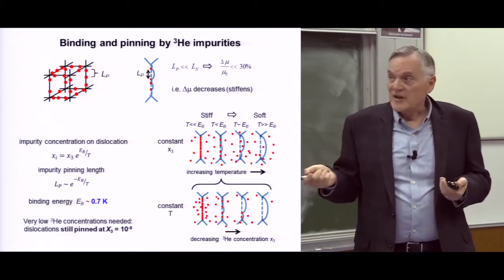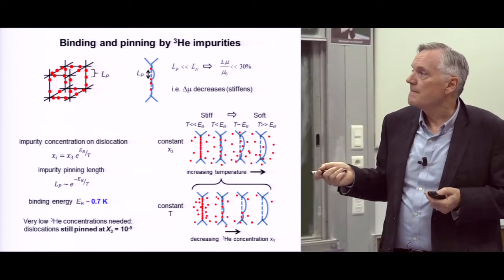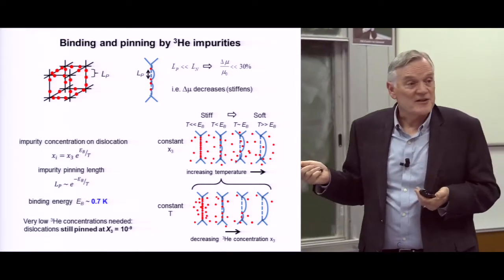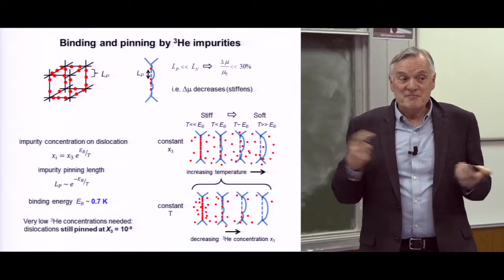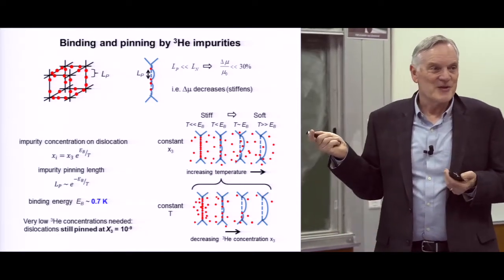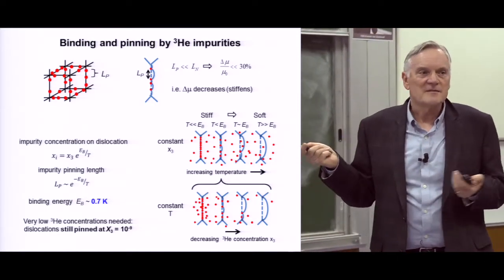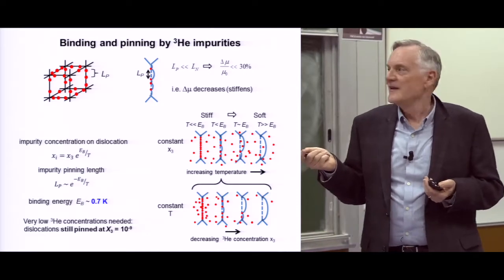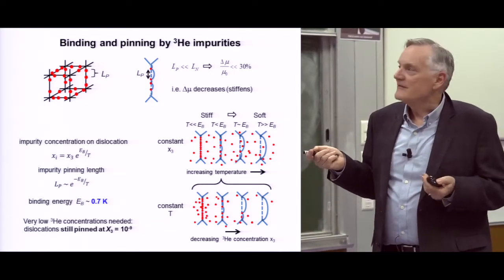And this is a perfectly reasonable way to look at it. But it doesn't take very much. I mean, to your point, 10 to the minus 9 is plenty of helium-3 to pin all the dislocations if it all goes there, even less. 10 to the minus 10, 11 probably is enough to pin them, which is very hard to get rid of.